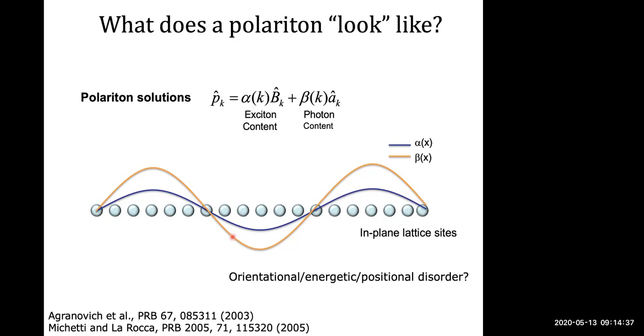So what you tend to find is that the wave vector of the photonic part is fixed, and this is determined by the field distribution. But what disorder will do, because the disorder is only in the excitonic part, is to localize the excitonic part in space. And this is really nicely highlighted in the second reference if you want to see an example of a 1D simulation where you just diagonalize this Hamiltonian, adding disorder to the excitonic component. So you'll find that if you take the k-space solutions and Fourier transform, or you do it directly in real space, you end up with localization in real space, especially for the excitonic component.